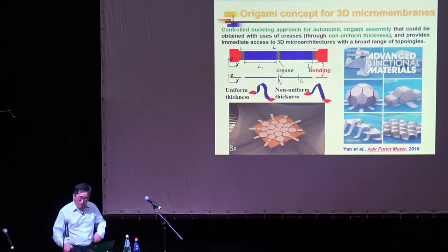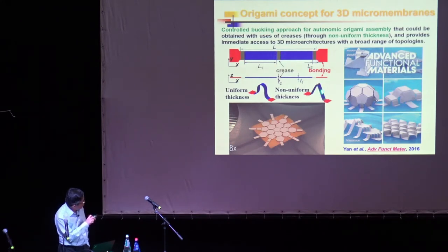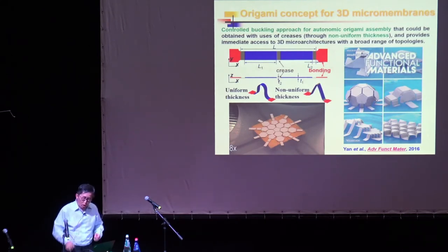So once the structure pops up, the gray area here with a reduced cross-section takes more strain, so deformation tends to concentrate on those gray parts to form the sharp edge. Okay? So by reducing the thickness, you induce larger deformation at those cross-sections. Those serve as hinges. Then they can produce very sharp transitions between the straight parts.